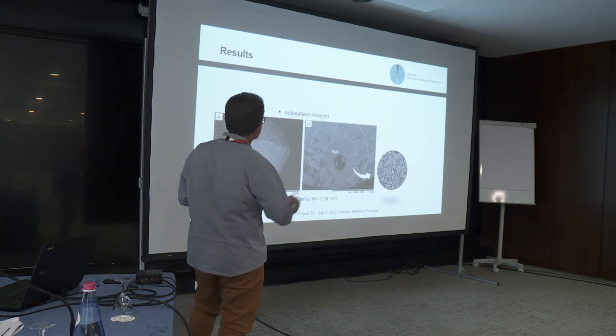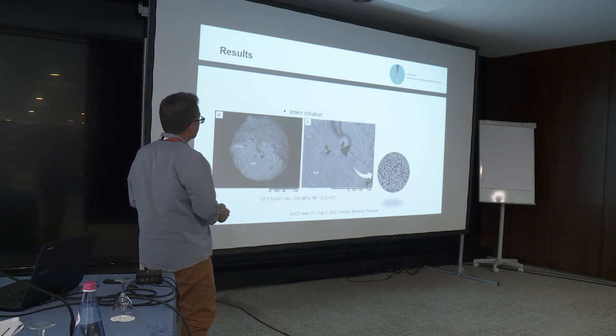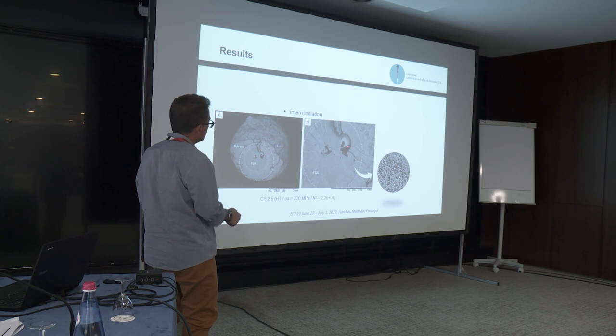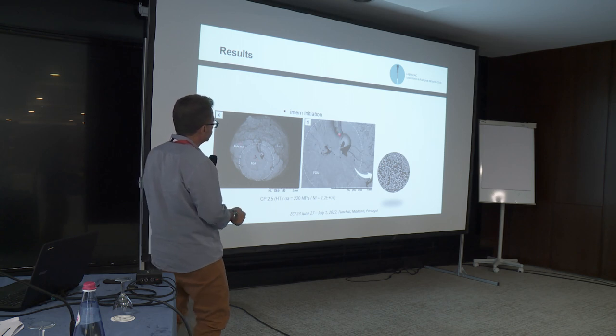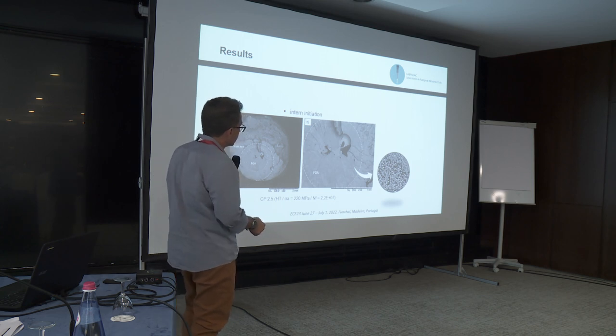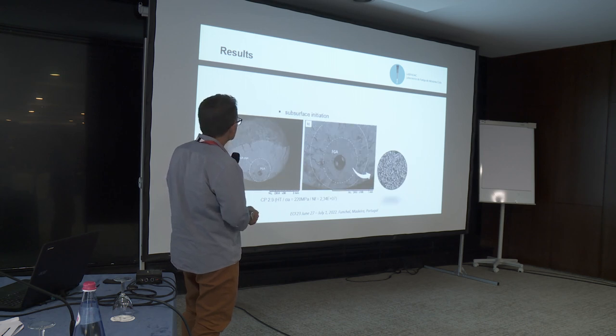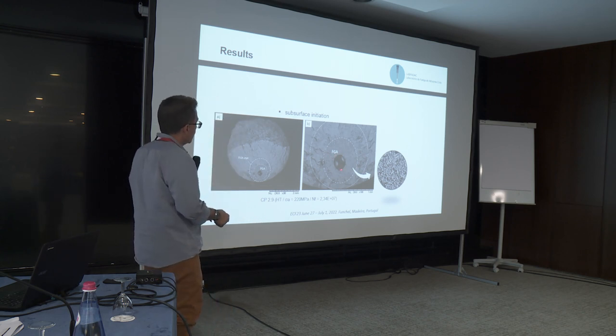So for the internal initiation, also at an inclusion, we have the fine grain area surrounded by the fish eye area. Here we can see the roughness of the surface. And also subsurface initiation, also at an inclusion, surrounded by a smaller fish eye and also a smaller fine grain area in both.